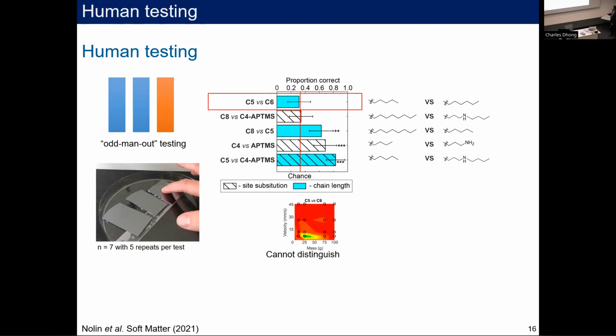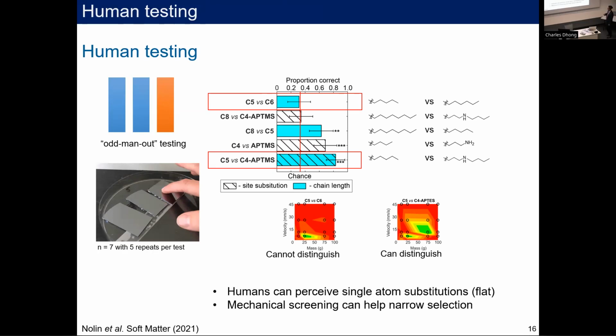And so if we see this, then we can say, well, did this actually correlate to some of our mechanical testing? I would say yes, somewhat. We got a hint from our mechanical testing that this would be different and this would not be different. So it's our way of screening through mechanical testing what humans might do. And also this helps us find that maybe some of these subtle effects, the reason why touch is so hard to recreate is because we don't have a lot of new ways to recreate touch. So maybe by using surface chemistry, it opens up a much wider avenue of different ways to stimulate the sense of touch.